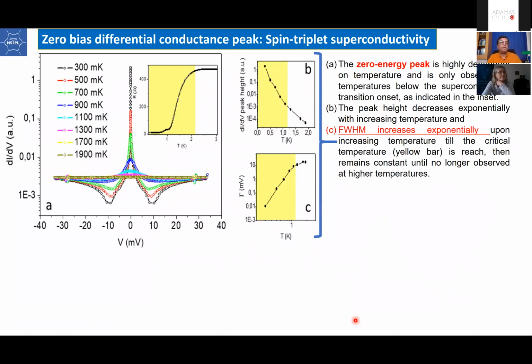So what is the proof? Once again, if you perform the differential conductance, so you do IV measurement, current versus voltage, and you convert this into the differential conductance, and you perform this measurement at different temperatures, 300 millikelvin onward. You can see at zero bias, zero field, a strong peak with some satellites, which is temperature dependent. I'm not going into details because that's not the main topic of my talk. But what I want to say is this is a very, very important signature of a non-BCS type superconductor, an unconventional superconductor. It's very difficult to see in normal superconductors.